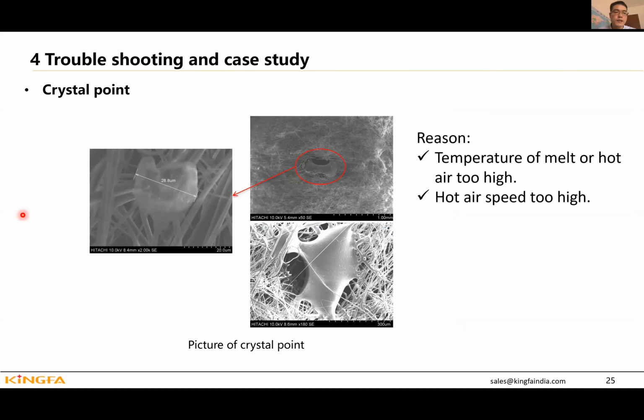Okay, we go to the last part, which is about some troubleshooting and case study. During our production, some defects will come. The first one is the crystal point. In this SEM, we can see this particle is about 28 microns, so it's very big. This is because during the meltblown, the temperature of the melt or hot air is too high, so it's not cooled enough, and then the melt comes to the collector and stays in our fabric. So we should address this reason, and we can have some solutions to decrease this crystal point.